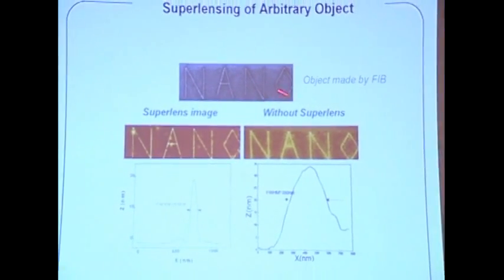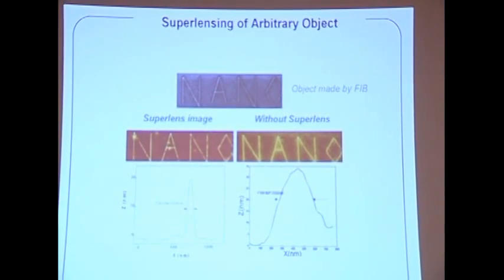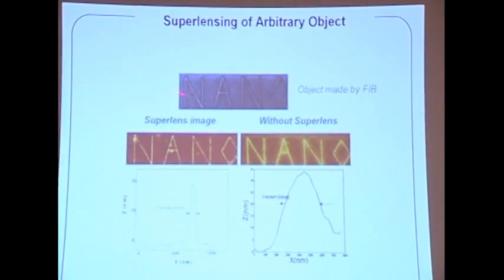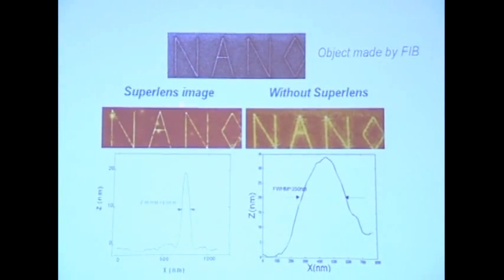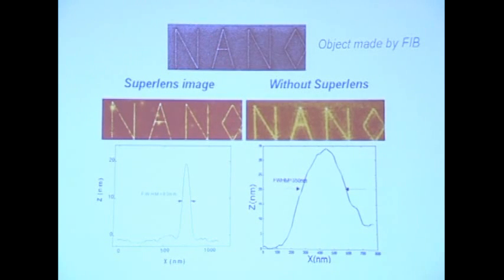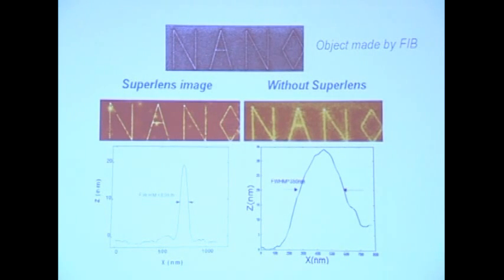And in addition, we demonstrate arbitrary pattern imaging. You write the nano characters, where the line width is about 50 nanometers, but the character itself is about 1 to 2 micron. So the character is diffraction limited, and you should be able to see the overall structure. But if you do a Fourier transform of this object, there are all kinds of k-vectors. The largest k-vectors correspond to this very small feature size, and small k-vectors correspond to the bigger overall size. So without the superlens, you will see the overall structure.